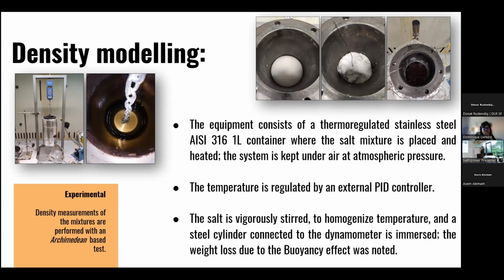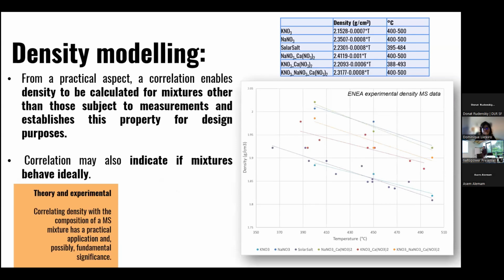And the temperature is regulated by a controller. And the salt during the test is stirred to be homogenized. And a steel cylinder connected to the dynamometer is immersed. So the weight loss due to the buoyancy effect is recorded. Here are the experimental results of this campaign.